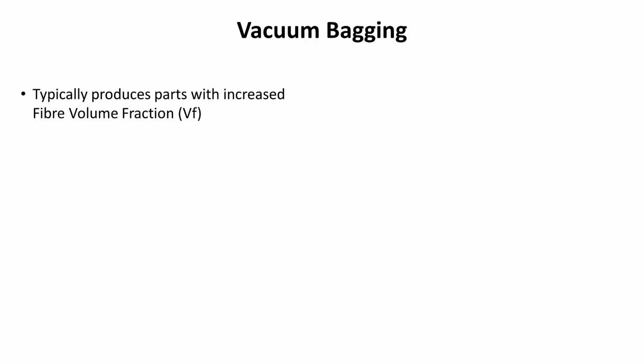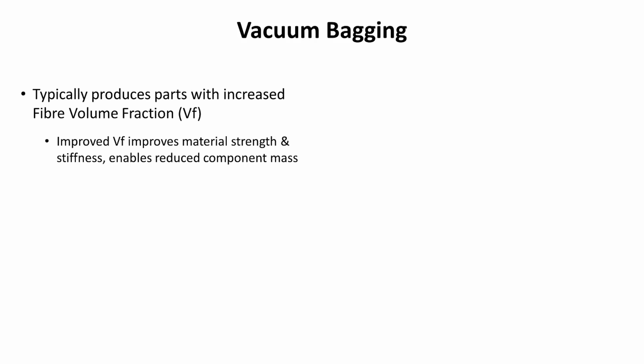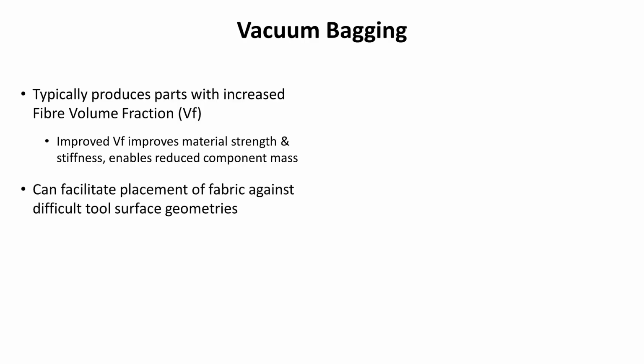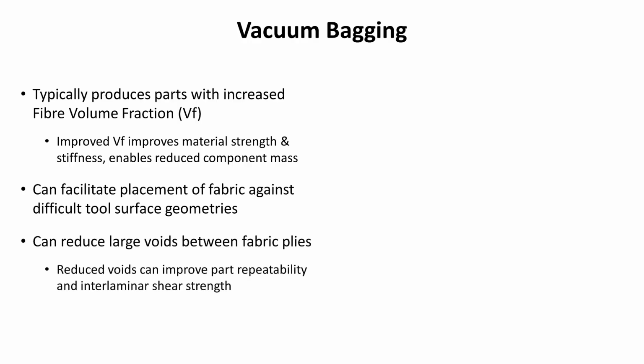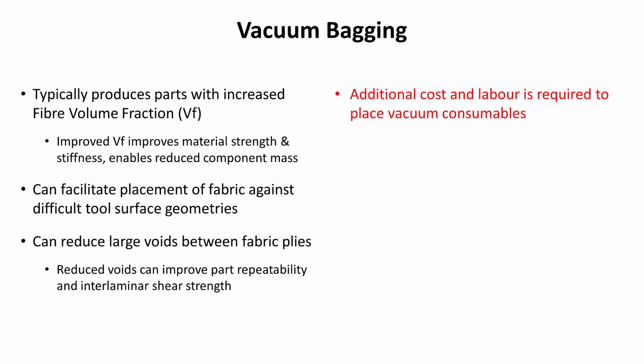If a requirement for a part is low weight, high mechanical properties, and repeatability, the superior fiber volume fraction produced by vacuum bagging will typically outperform an open-air cured part. When a part has many tight curves or corners, a vacuum bag helps hold the fabric in place against the tool. Vacuum bagging may also reduce large voids within the laminate. A disadvantage of vacuum bagging a part is increased layup time as well as equipment and consumable cost.